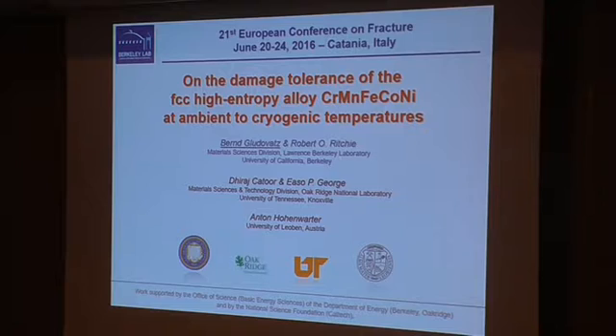A few years later, when our now collaborator Easo George got interested in this single-phase FCC material, he first of all wanted to identify that this was really a single-phase material. So he arc melted and drop cast the same combination of elements and then heat treated it subsequently for 72 hours, so basically 3 days at 1000 C, just to be able to say that Brian Cantor was right, everything is correct, that this is a single-phase material. Due to this long-term heat treatment, he was also able to say this was a stable single-phase material.